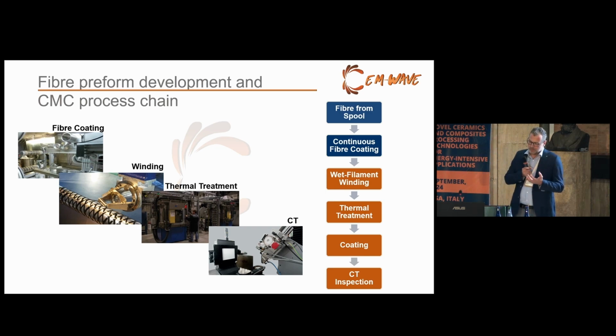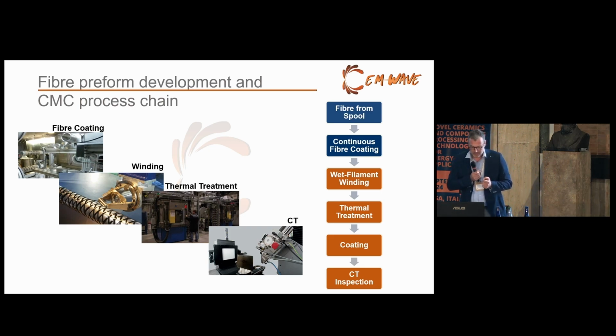And you can cover the material in such a way that you can protect your CMC during the high temperature influences by some different kind of gases and temperatures. And of course, the coating should not fall off or do some strange things like craquelle structures and so on, where you have no coating, and at some points this is not so good. And this you have to keep an eye on.